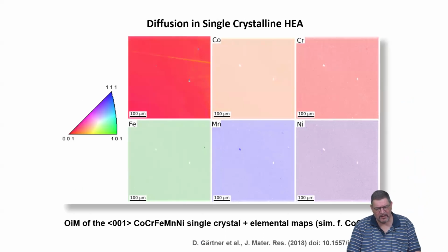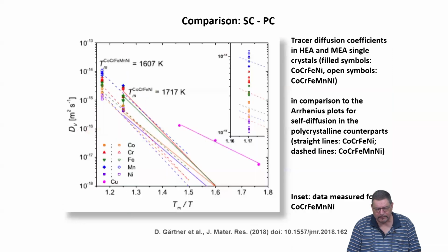Going to single crystals, back we saw the first results beginning with this chapter on volume diffusion in high entropy systems. This shows you the single crystal which we experimentally had, which was obtained in Poland with a collaboration partner, where they are specialized in growing single crystals. And you see that there is a common orientation and no chemical heterogeneity on the scale of SEM EDS measurements.